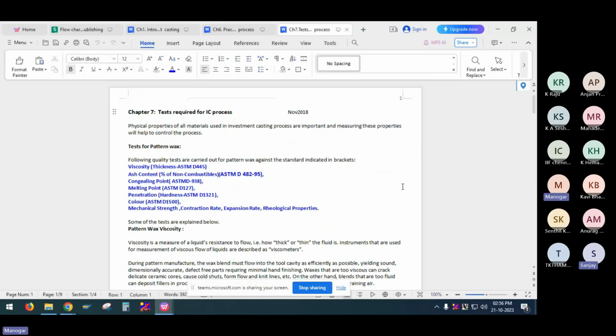See, I am going to take today mainly the test records in the investment casting process, because most of the foundries are lacking testing or process control. So I'm going to cover today most of the test requirements in the investment casting process, step by step. First, tests for the wax pattern, that is for the wax used for pattern making: viscosity, with a bracket given showing the standard applied for the particular test, ash content, congealing point, melting point, penetration test, that is hardness, color of the wax, mechanical strength, contraction rate, expansion rate, and rheological properties.